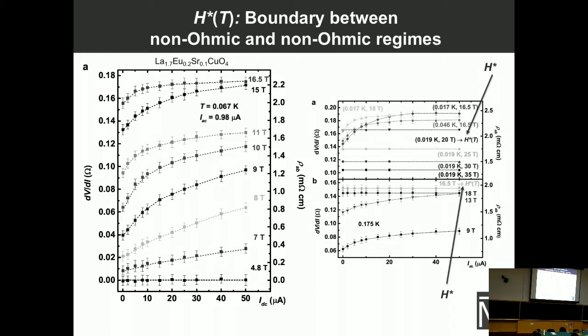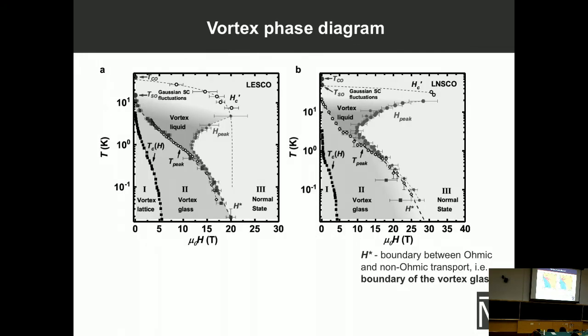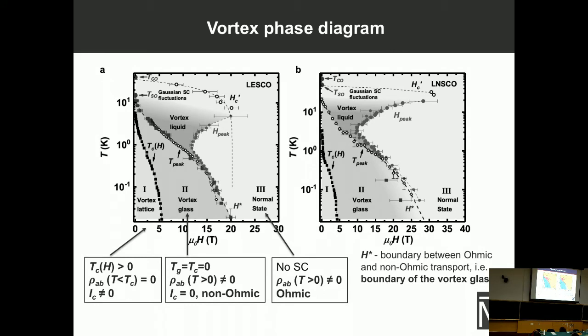So the transport is ohmic, and you can identify the field that we call H star, which marks the transition between the non-ohmic regime, these are H star, these red symbols, and there are some here, non-ohmic regime at lower fields, and ohmic transport here. So basically what we find are 3 experimentally distinct regimes, as one expects, as I described at the beginning. Here resistivity is 0, we have critical current, and here the resistivities are finite, linear resistivities, but the VI is non-ohmic, and here we find ohmic behavior.